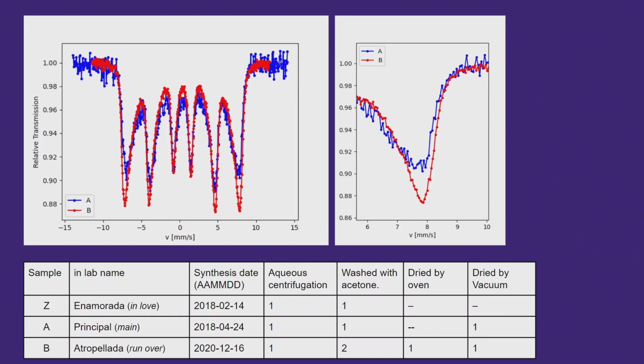Okay, we made the synthesis, and when we checked with different techniques, in the case of Mossbauer, we see this situation. It was not so different. They are normalized by area, but there is some difference. This line is narrower than the other one, so it seems that the particles are bigger in the new synthesis related to the first one.